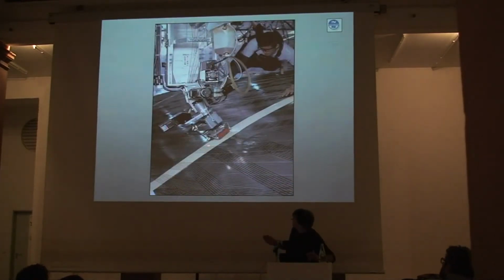So let's take a better look at the fiber placement head. There's spools of fiber up here out of the picture, which drop down through the head. You can see there's a resin reservoir there, and there's a resin bath, 20 mil resin bath, right in front of the tire there. The fiber's pulled through the resin bath and wetted out with adhesive just before it's laid down on the surface of the mold.